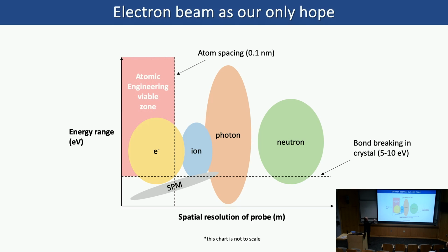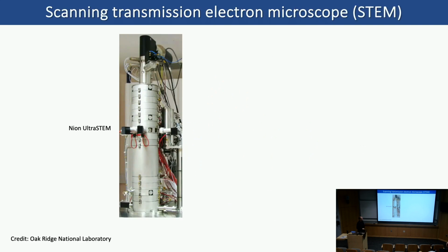And then I just highlight this area. This area is what I call the atomic engineering viable zone. So you need to have a technique that has a higher energy than this bond breaking line, and you need to have a higher spatial resolution than the atomic spacing. And you can see that electrons might be the only technique that we're able to do atomic engineering with at this time. So that's why all my following talk will be based on TEM, or electron microscopy. So that's why we do electron microscopy for manipulating atoms.